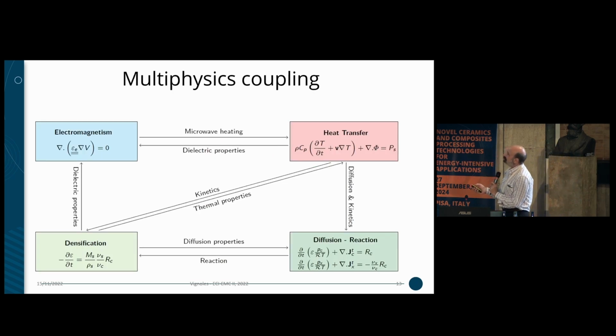So this gives you some ideas of multiphysics coupling, because densification is the equation here for the evolution of porosity. Heat transfer here is for the evolution of temperature, and diffusion reaction is for the evolution of the reactant. Okay, so we got three of them. But of course, heat transfer is also a combination of heat consumption, heat losses, and heat input, which comes, in our case, from electromagnetism. So this gives the fourth block of this multiphysics coupling.